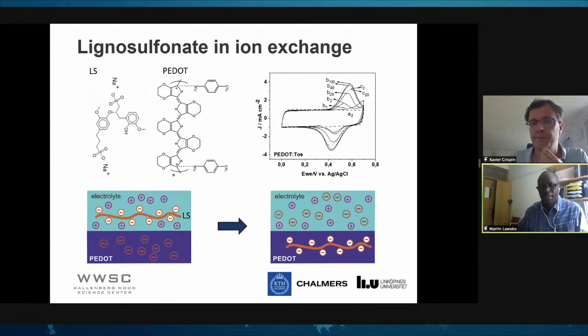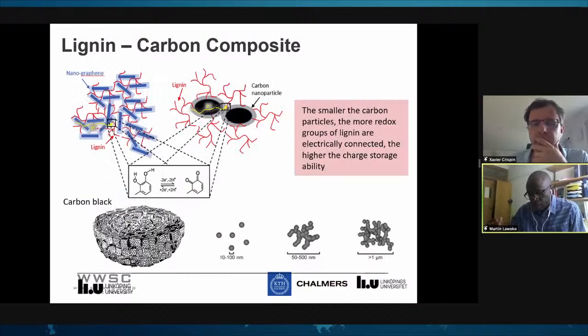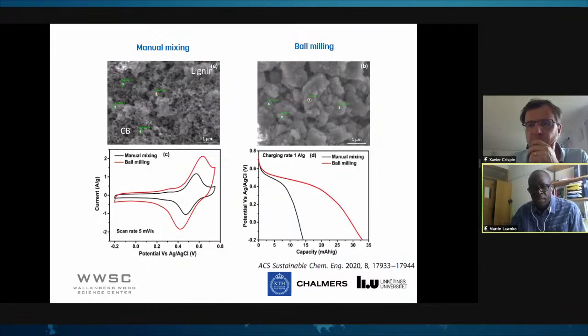Okay, very interesting. And as we wait for more questions, maybe I can continue. You showed very clearly that in this carbon black there is some kind of lack of contact that might affect the efficiency of your lignin. So you performed this ball milling on your carbon material, and then you show very clearly that the efficiency is improved. Now, one problem could be related with the energy that you have to put into the ball milling. Could this be mitigated by instead using smaller lignin molecules that would have better contact with the non-milled carbon black? Do you see that as an alternative?